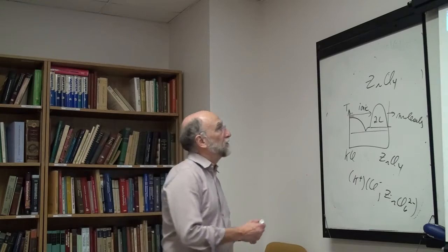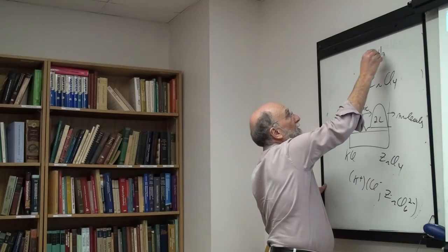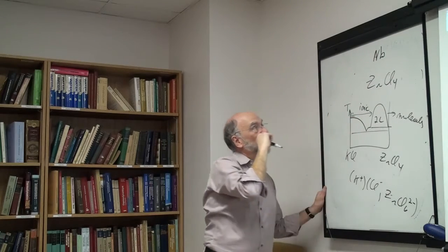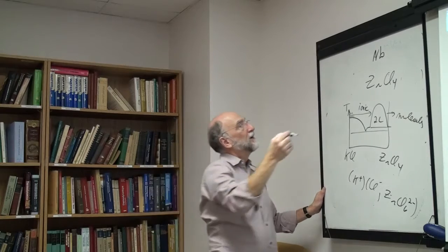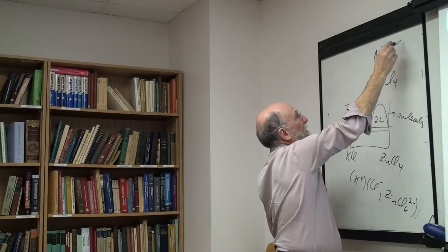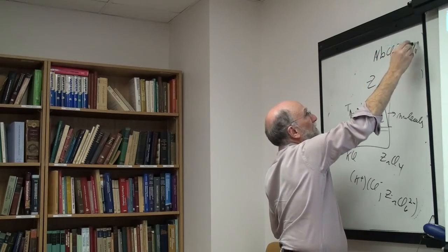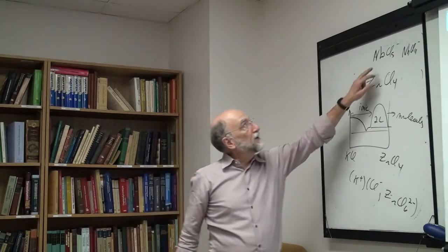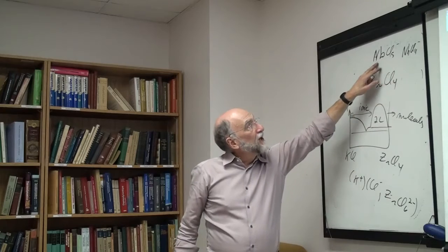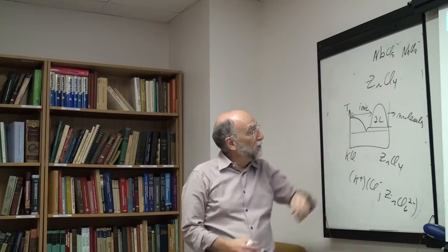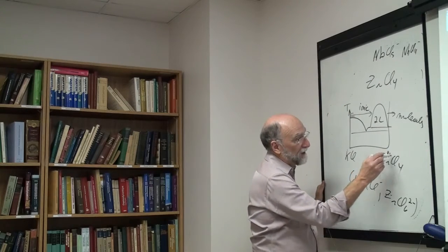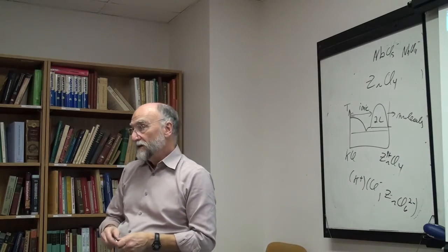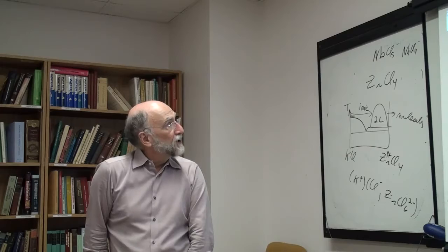Okay, so other things like niobium, but not enough data, but when you have highly charged cations, niobium can have 4 and 5. You could have NbCl5, you might have NbCl4. Again, the tendency is to form strong complexes because these are highly charged. Zirconium is highly charged. It's relatively small, but it also has an extremely strong charge. Okay, when I said the size affects it, also the charge affects it.